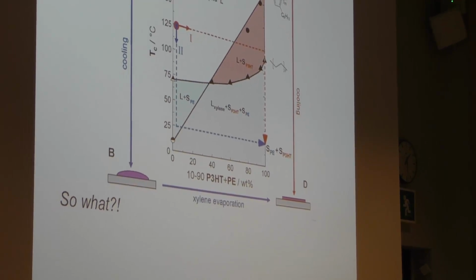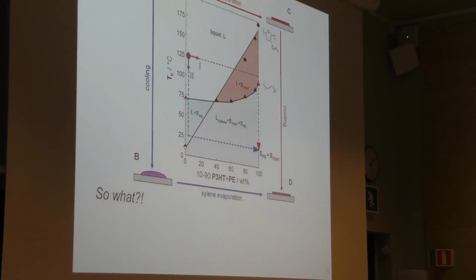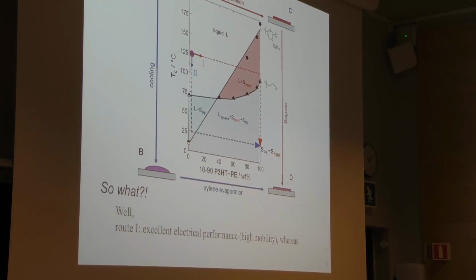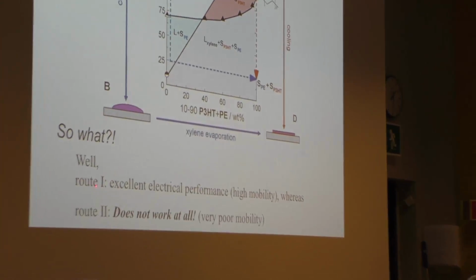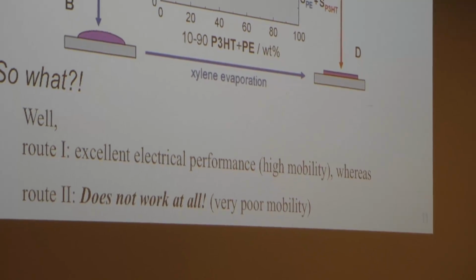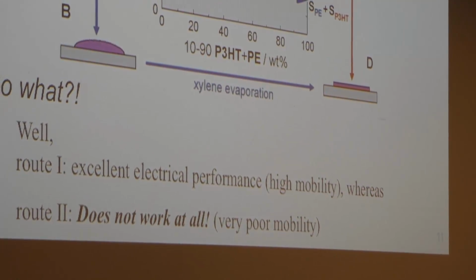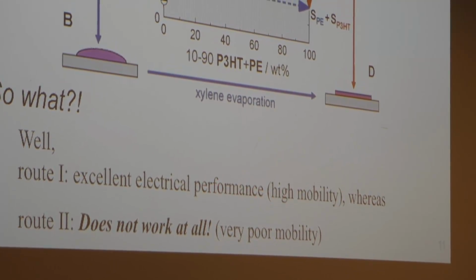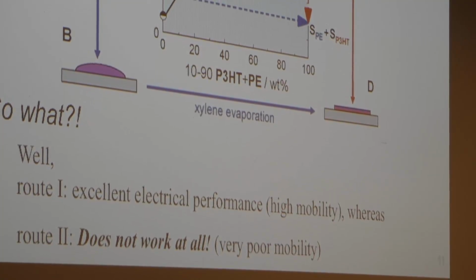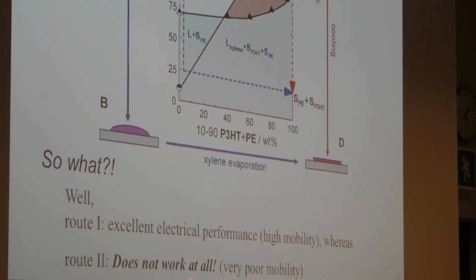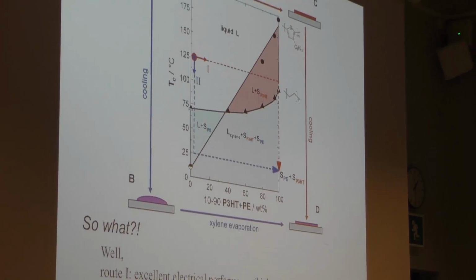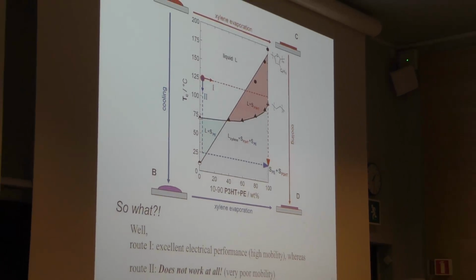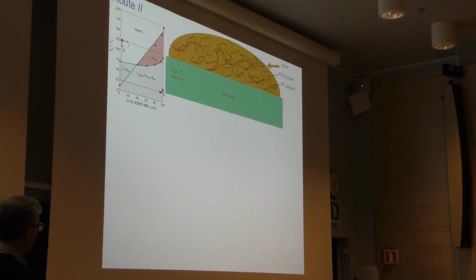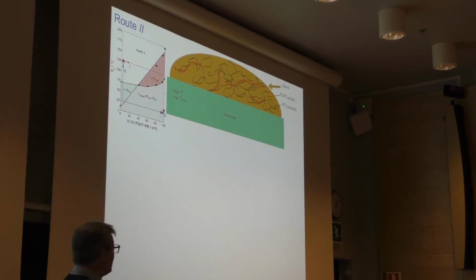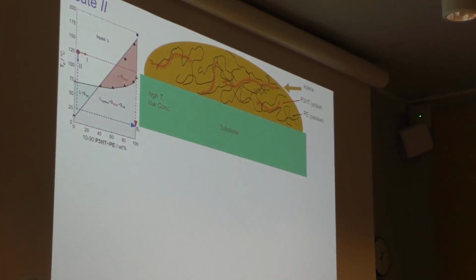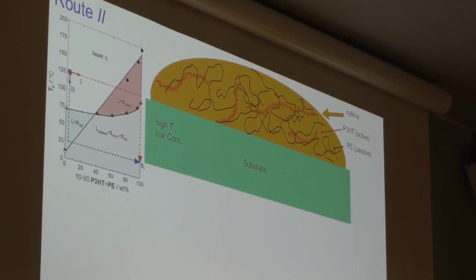the answer to that is that this makes a dramatic difference, because if you look at what happens if you follow route number 1 here, you get an excellent electrical performance in terms of high mobility, whereas if you follow the other route, it does not work at all, in the sense that the mobility is very poor. This can again be understood using grazing incidence as one of the tools.